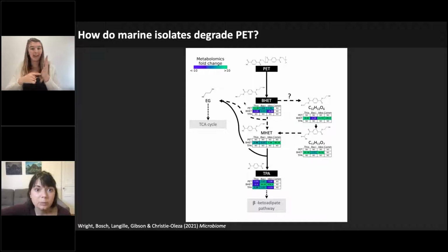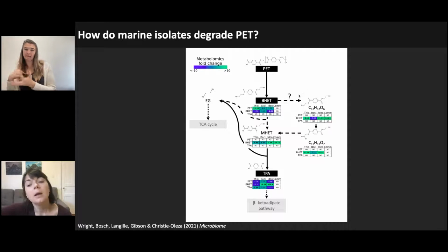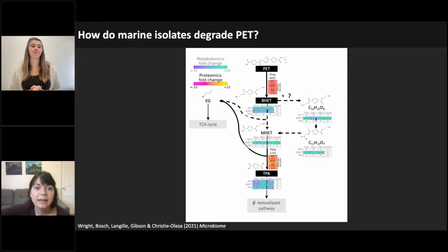So when we incubate with PET, we detect BHET. When we incubate with BHET, we detect MHET and terephthalic acid, and so on. And we also have a couple of extra intermediates that we're not entirely sure on the pathway for their degradation. But we also find that for the case of Thioclava, we have enzymes that are very similar to those used by Ideonella for each of these steps, and that these are more abundant when we're incubating with the PET or the BHET, for example, than when we incubate with the fructose. So we have an enzyme similar to the PETase and also one similar to the MHETase, as well as enzymes for all of the downstream steps necessary to actually use both the terephthalic acid and the ethylene glycol for growth.